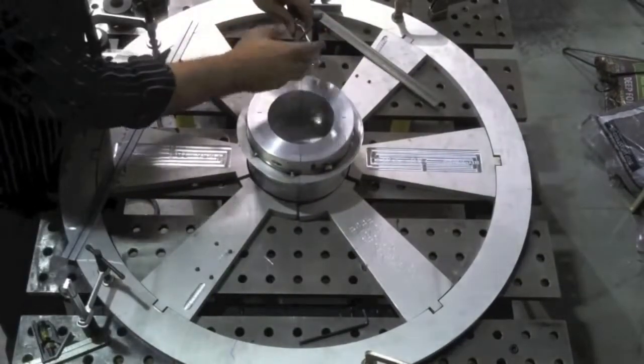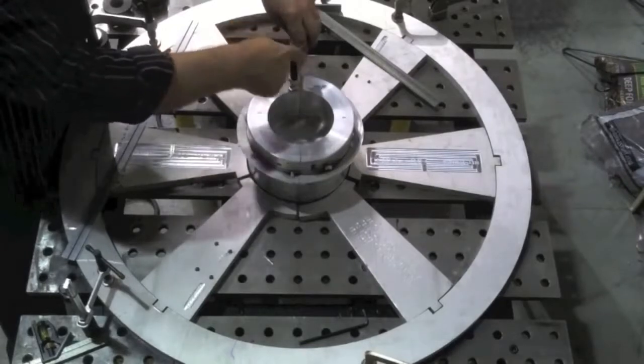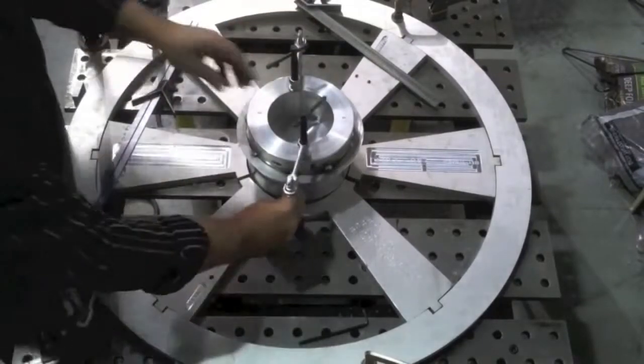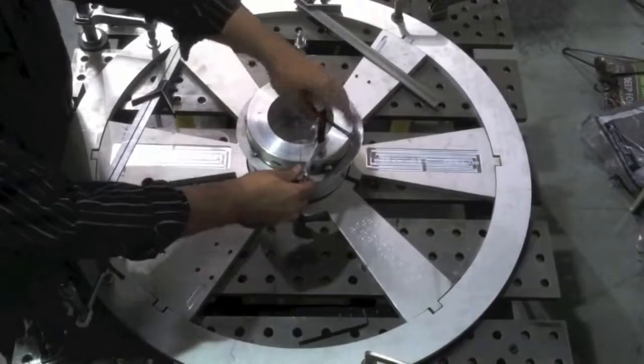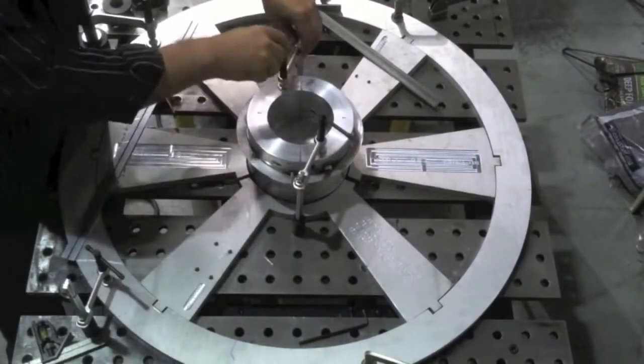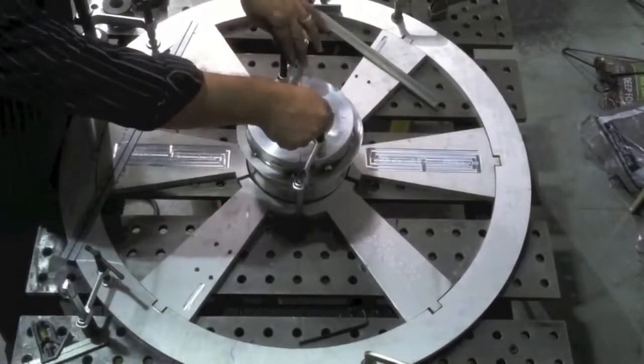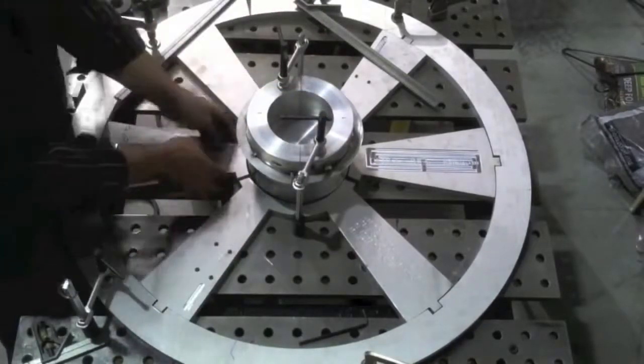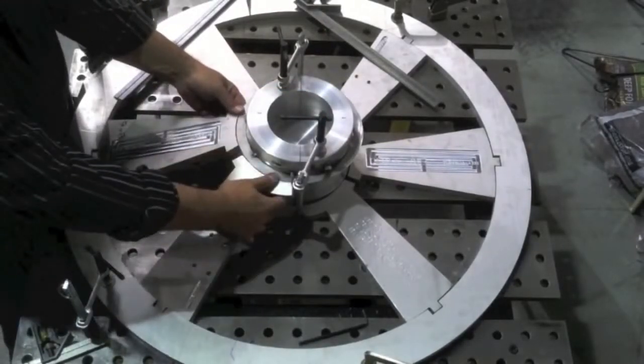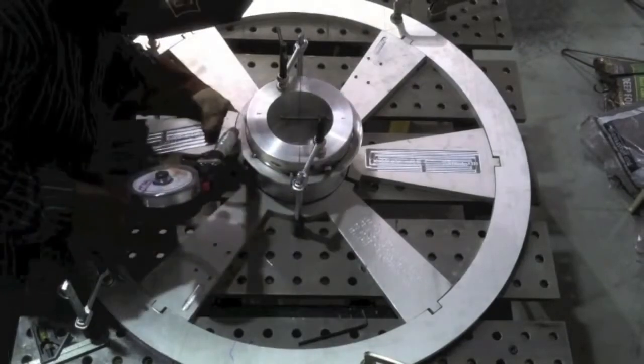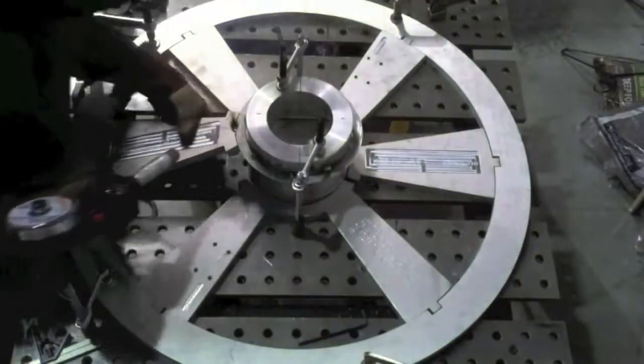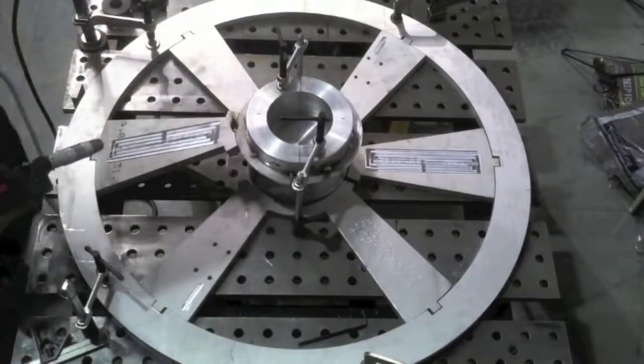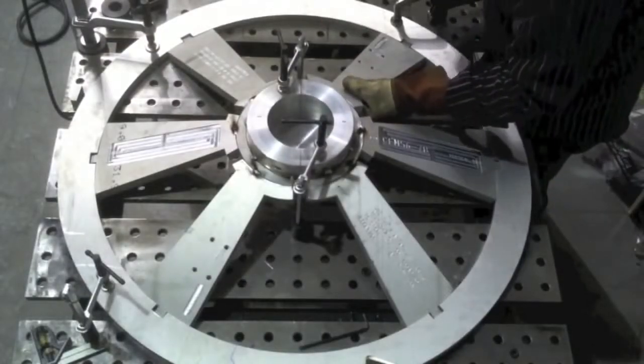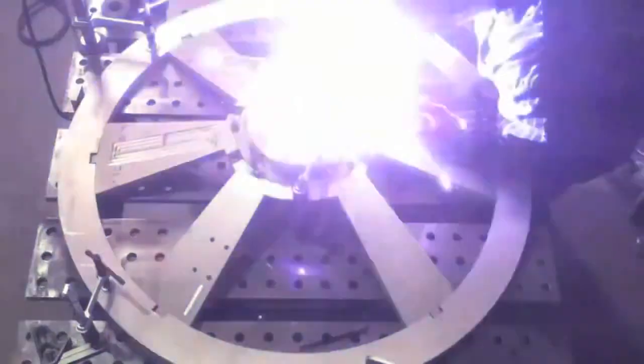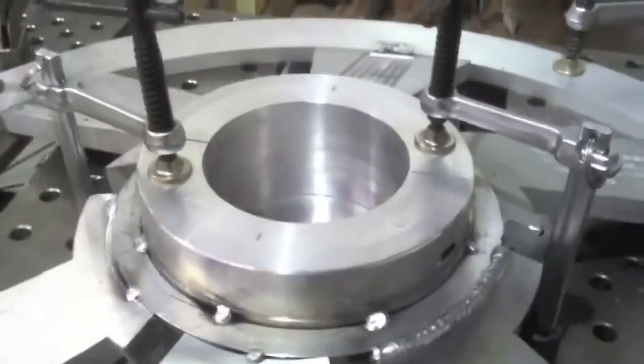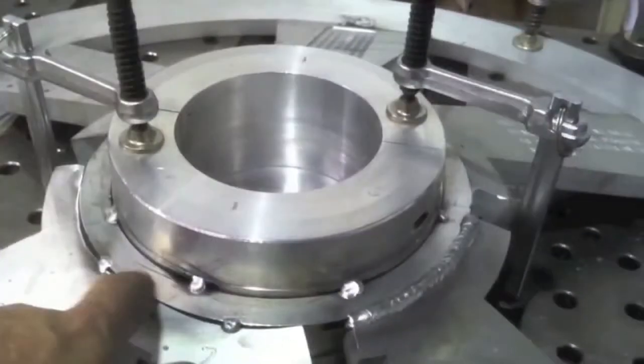Because you can see that center hub is pretty thick. That's almost 2-inch thick aluminum in the hub, and then the rest of it is pretty much 3/4 inch 6061 T6 aluminum plate. So it's quite a heat sink, in other words. So no matter how much power you have with a spool gun, it's going to try to draw the power out and resist flowing. So the hotter you can, to an extent anyway, if you can get some preheat in there, it just makes everything go a lot better. You have to use a lot less energy from the gun if the metal's already hot.